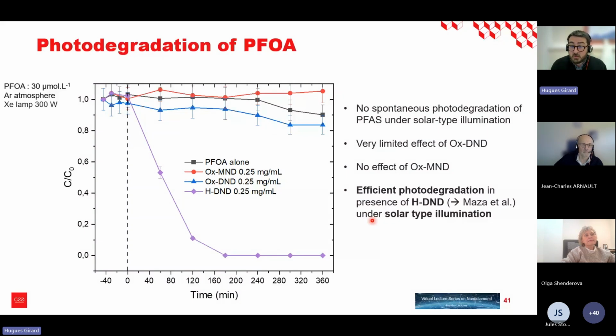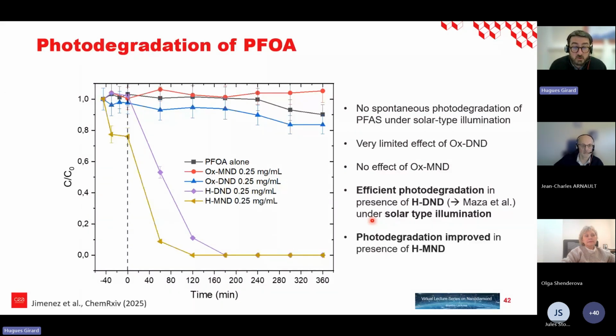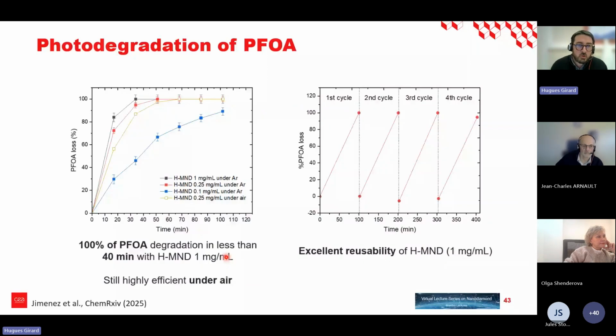And what was very nice is that finally, if you play with the type of nanodiamond, so with the milled one, then you can really increase the efficiency of the system. You can see here, at the beginning, you have a very strong adsorption at the surface, which really helps to degrade the PFOA. And as we tested also, there is a real improvement of the degradation efficiency thanks to this milled nanodiamond.